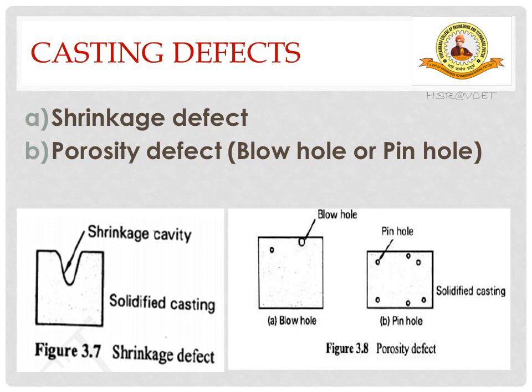So how to overcome? Some of the remedies are: use large risers to promote directional solidification. The location of the risers and gating is very important, so you have to choose the correct position, and gates to be cut as wide as possible so as to reduce the shrinkage effect. Moving on to the porosity defect, which can also be called blowholes or pinholes.